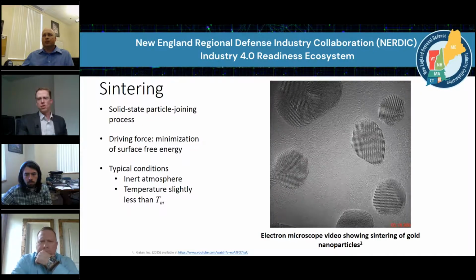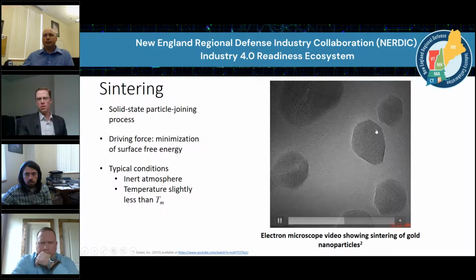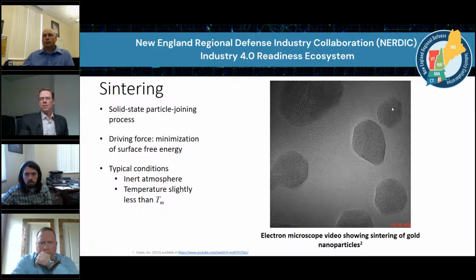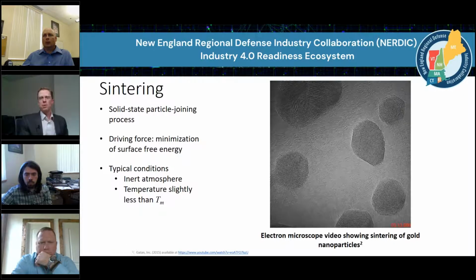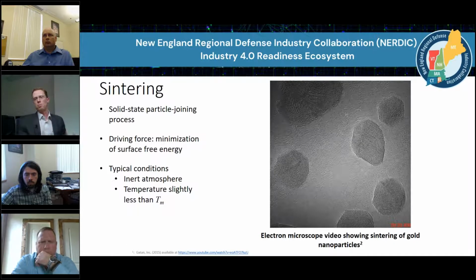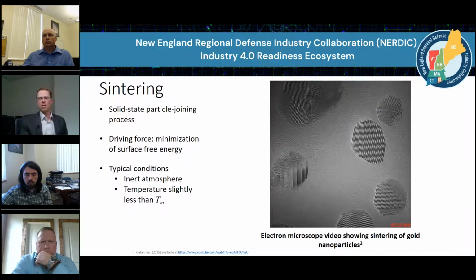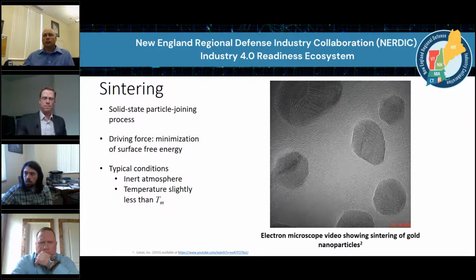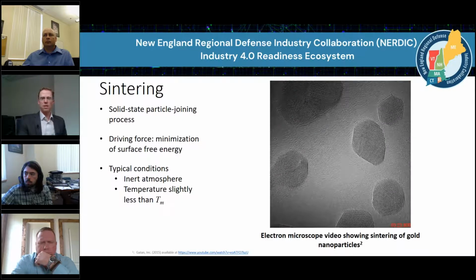For those that have never seen sintering before, here's an SEM image. These two particles will sinter together. Kind of back it up maybe. You'll see here's a particle, there's a particle. And it's a solid state process, and you typically raise the temperature just below the melting temperature, and the particles will fuse together. The driving force is a minimization of free surface energy, and it's important that it's a low thermal gradient process and that you don't end up with a lot of thermal distortions, or at least less so.